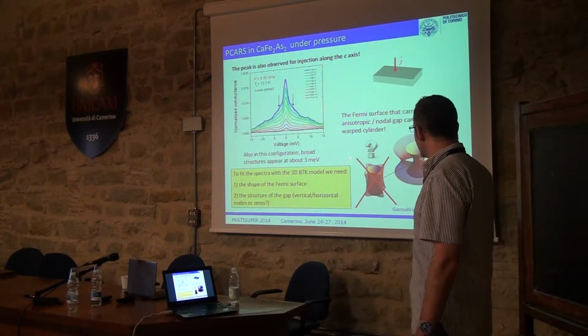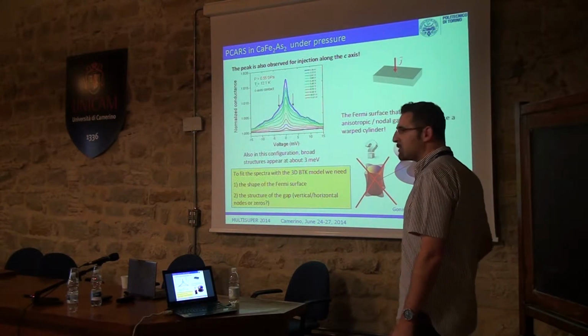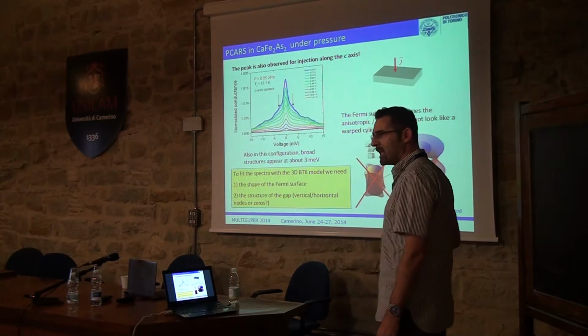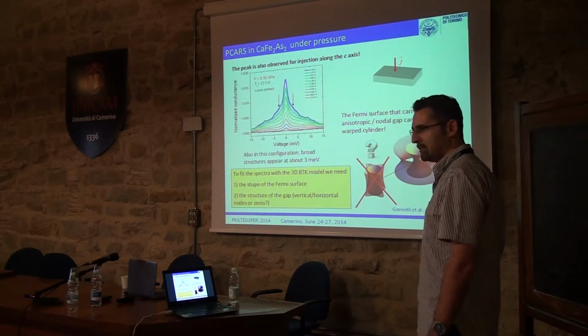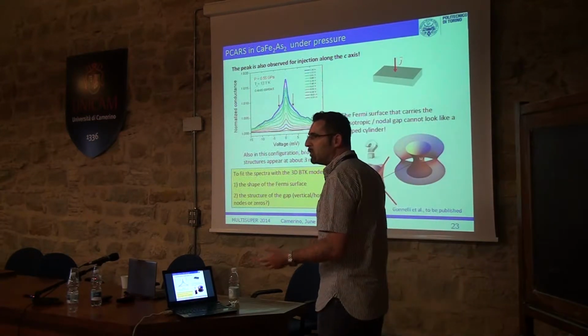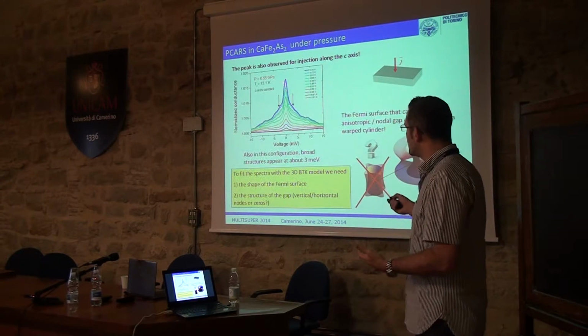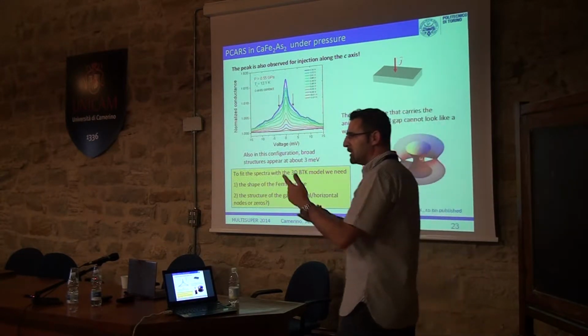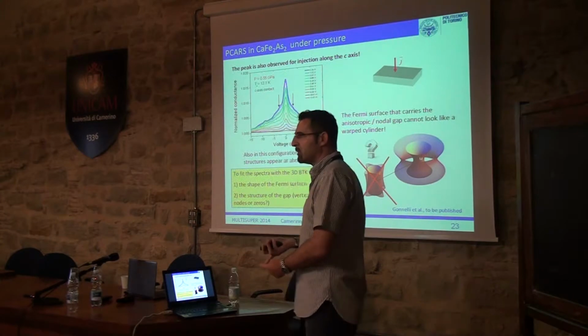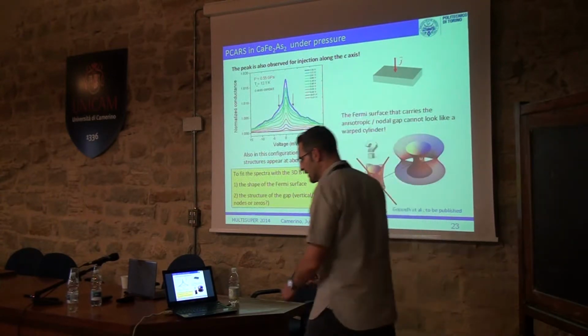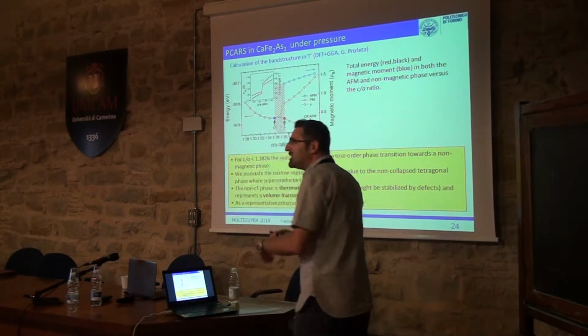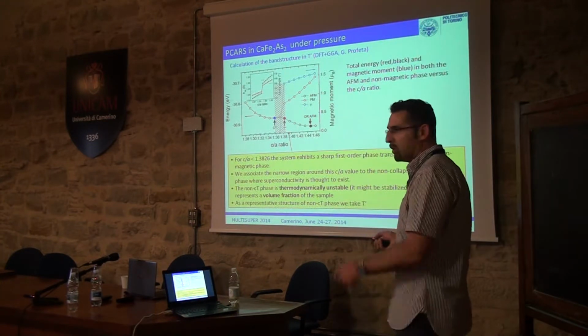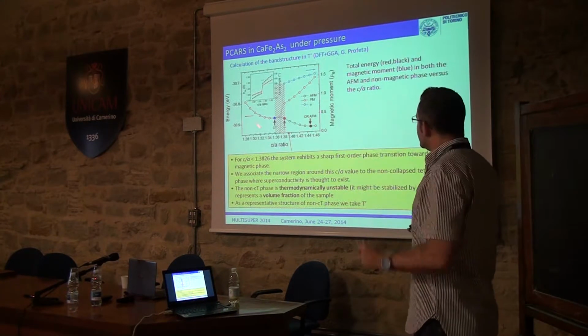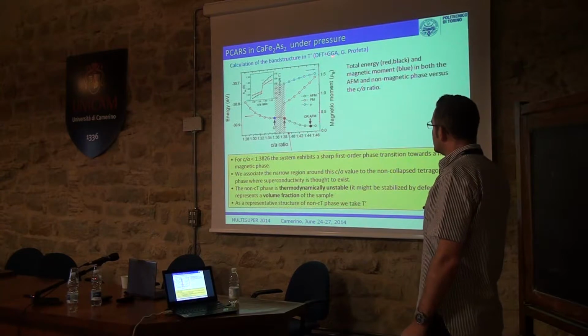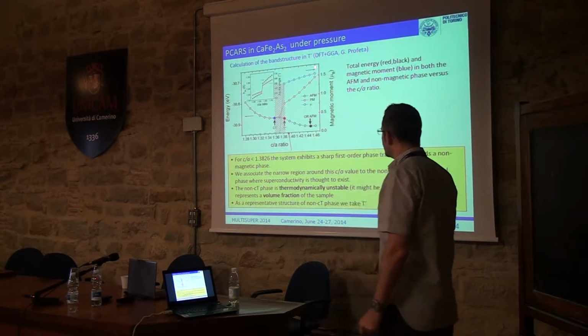So for sure, the Fermi surface that hosts this gap, the small gap, which is anisotropic, is not too big. To go further in the fit of the curves using the decay model, we need the DFT calculation of the Fermi surface and calculation of the order parameter structure to know exactly what is the shape of these nodes, or zeros. These structure calculations were made by Gianni Profeta.